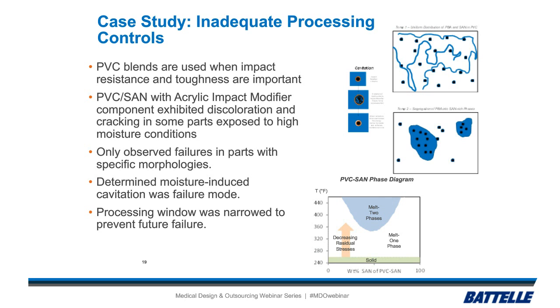And when we moved that processing window for temperature to the lower portion of it, we got a one-phase melt, which always makes good material. So for this one, just by changing the processing window to make it smaller, we were able to always get that one-phase melt and to eliminate this failure mode.